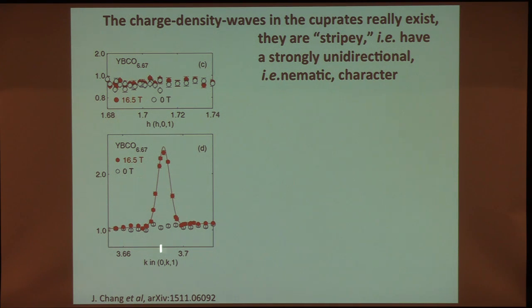What you see is that this is a very sharp peak. This corresponds to a correlation length of, I can't remember, a couple of hundred angstroms in plane. So that's the first thing. It's a very sharp peak. You don't have to do any background subtraction to see it. It's really there. The other thing that they really tried hard to make go away but couldn't is that this peak occurs in one in-plane direction but not in the other. So this is a unidirectional charge density wave. It's modulation in one direction. It's, if you want, a smectic phase of this material.